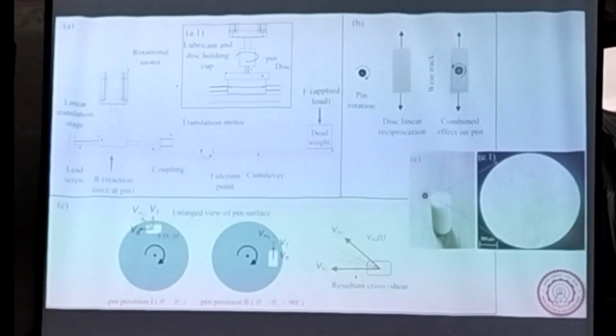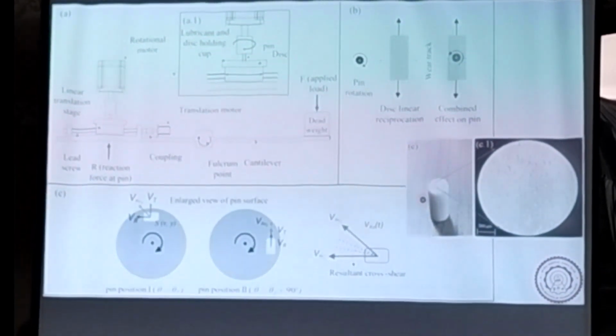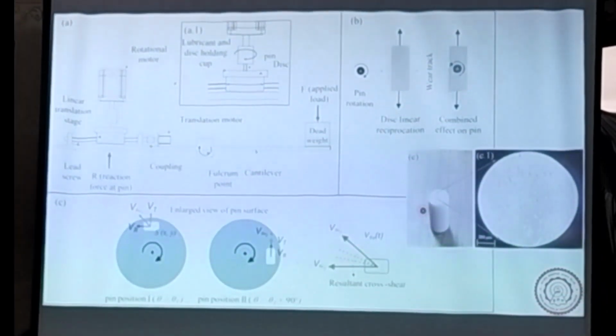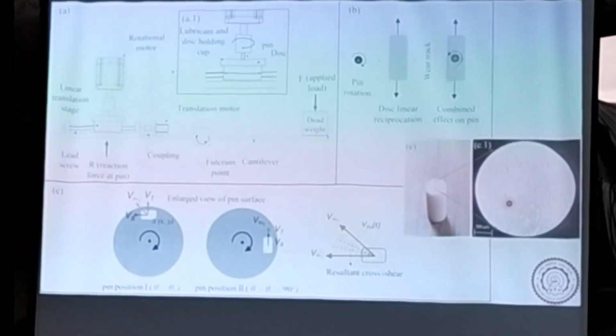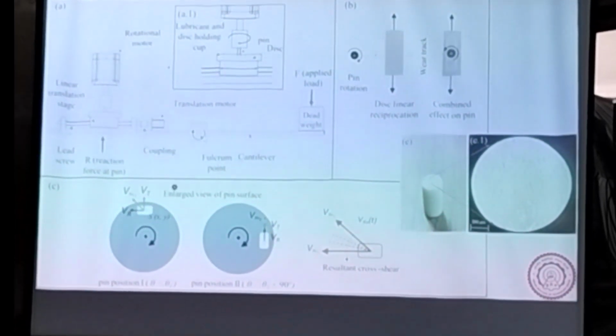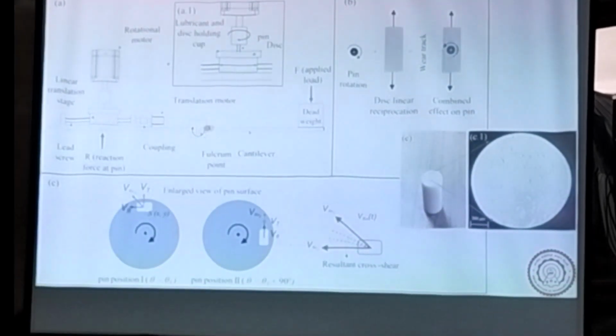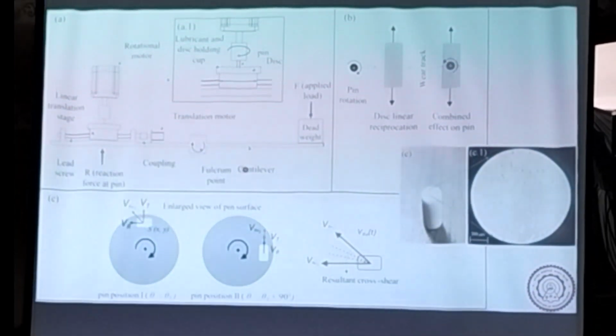Further on, we conducted a test where we have added a lubricant, a bio-lubricant. Hyaluronic acid is part of our joint material. So we have added it and made a further improvement in the composite. And this slide shows us the kind of test we have conducted.